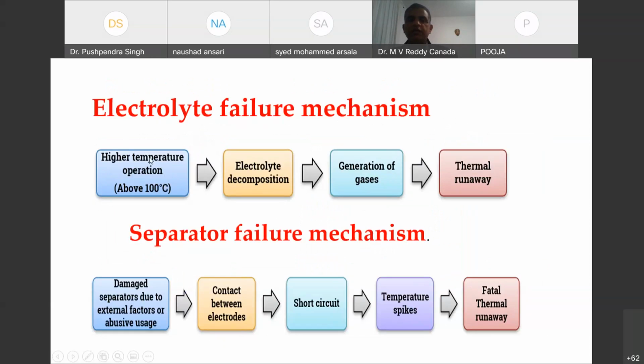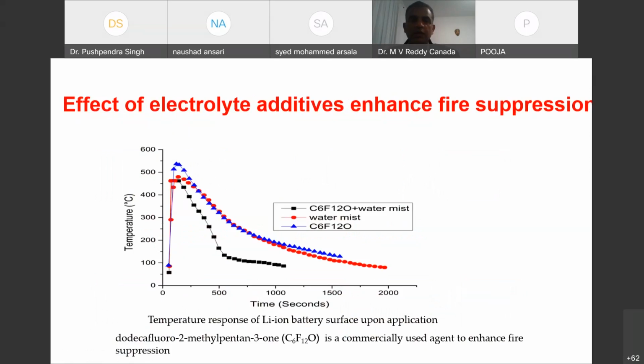Another failure mechanism: when you work with electrolyte, if you go to high temperature, there is also thermal runaway. Sometimes with separators, as I already mentioned, there is a short circuit with contact, which also leads to thermal runaway. If you cannot avoid this, people use some electrolyte additives just to reduce the heat. These are some typical commercial electrolyte additives we can use.